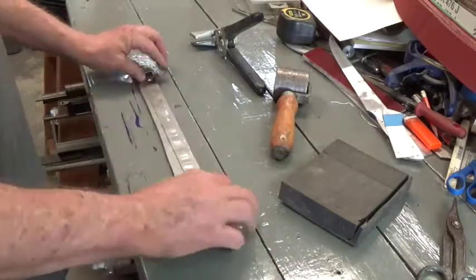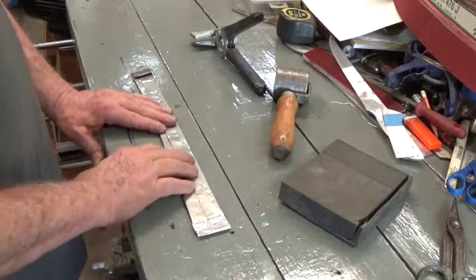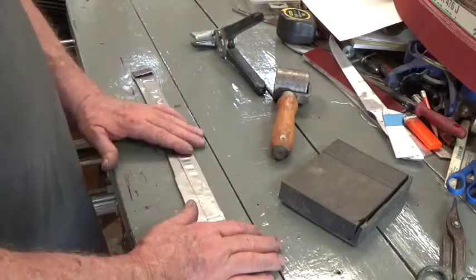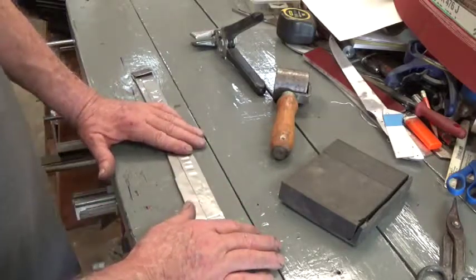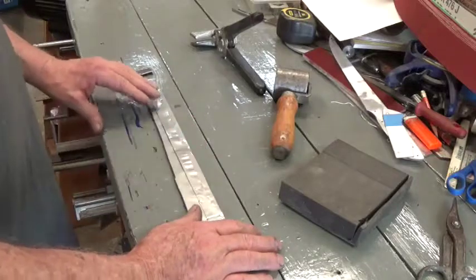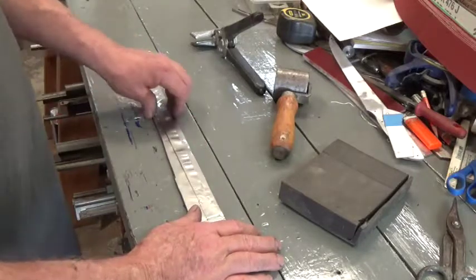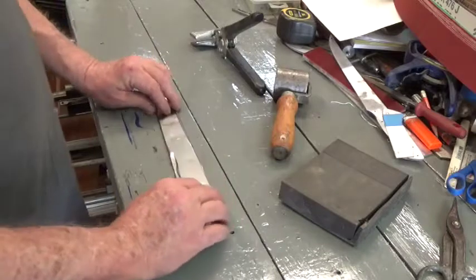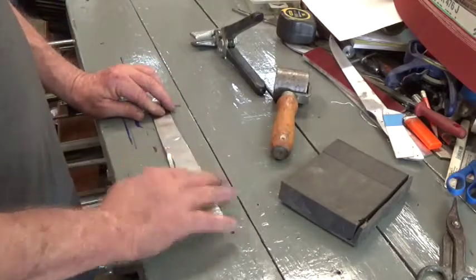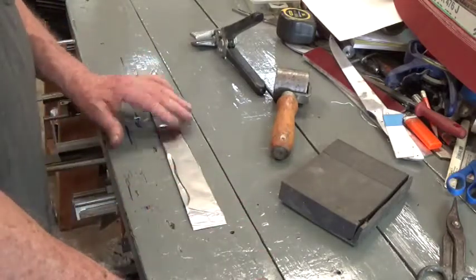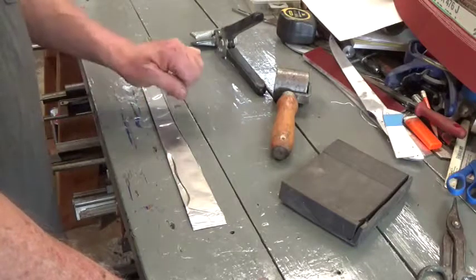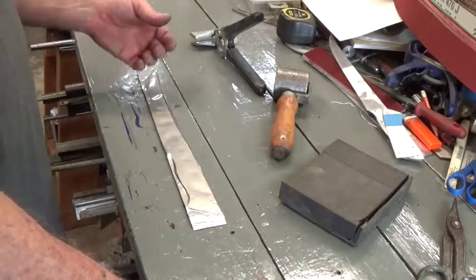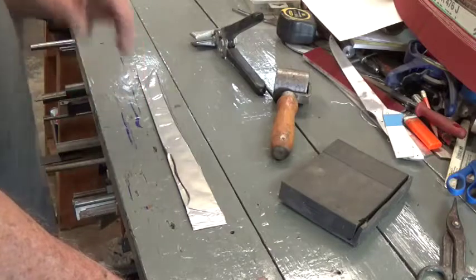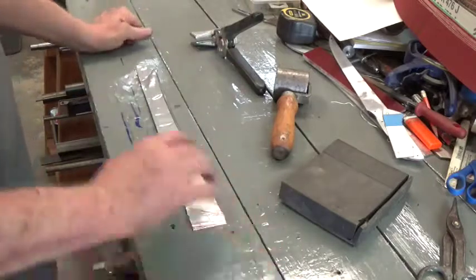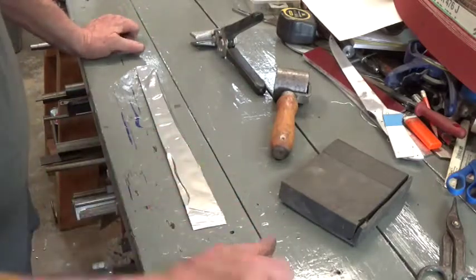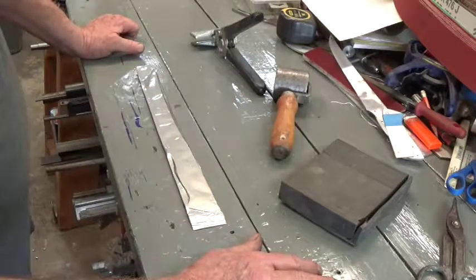So what we're going to do, we're going to harden this. After we bring it up to 1400 degrees and leave it for about a half an hour to normalize, we're taking it up to 1900 degrees. There it stays for 1 hour, after which it's brought down to below 125 degrees in oil. So I'll heat my oil up to about 110, and we'll do a long, slow quench. We'll leave it in there long enough to make sure it's fully brought back down.